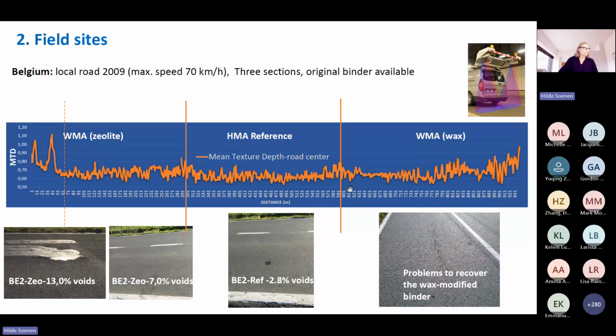Then we had a pavement in Belgium. This was a local road constructed in 2009. And in fact, this was a test site for warm mix. We had a warm mix section based on zeolites, replacing part of the filler with a zeolite. Then we had a hot mix reference section, and again a warm mix section based on a wax modified binder. Unfortunately, for this last section, we could not recover the wax modified binder. So this was not included.